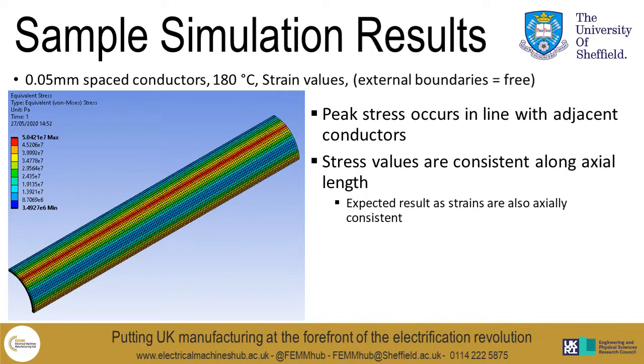So you can see from this slide the resulting von Mises stress across the coating layer. You can see that the peak value occurs in line with the adjacent conductors, and you can also see that along the axial length of the sample, the stress is relatively constant.